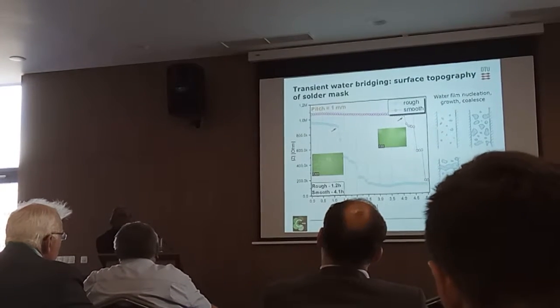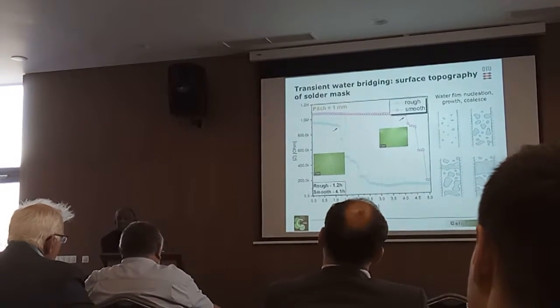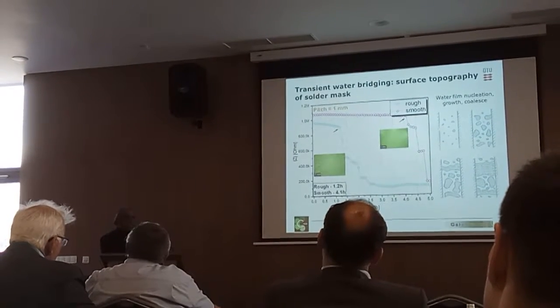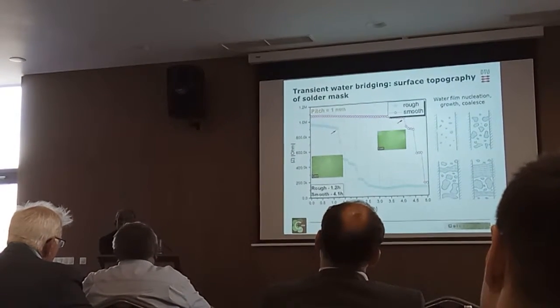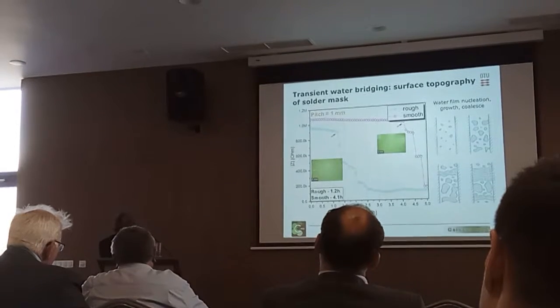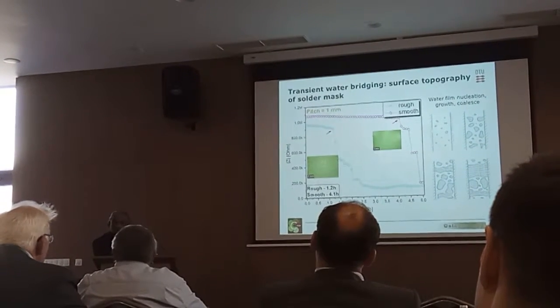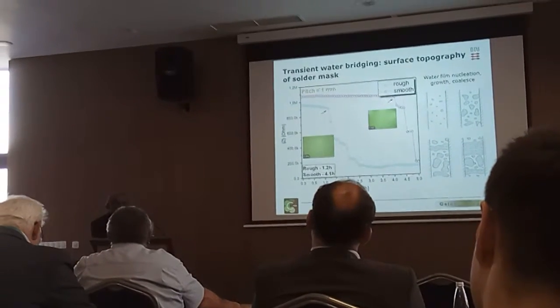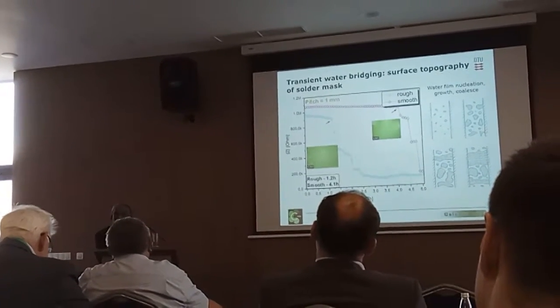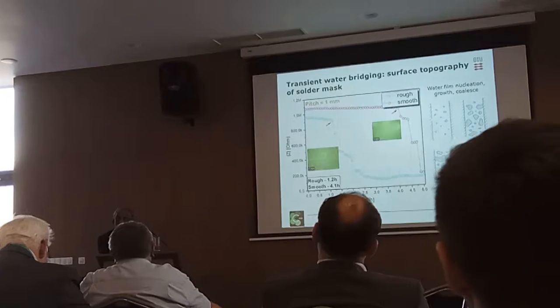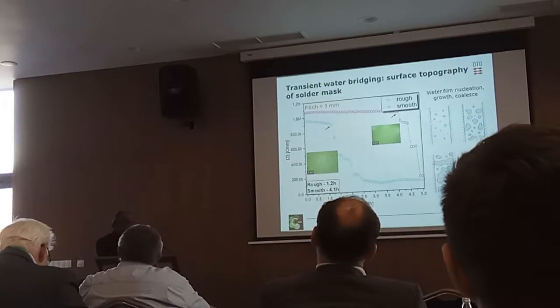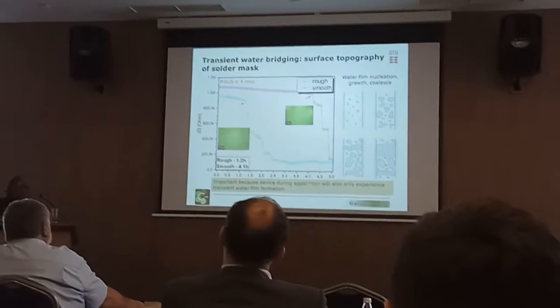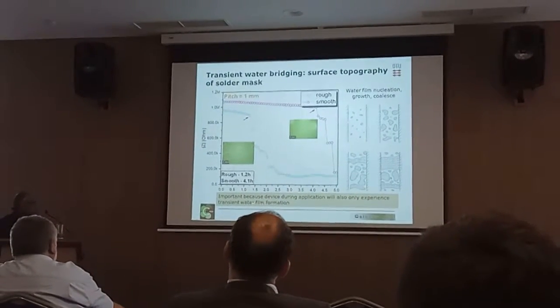So which means that if you can delay the continuous water layer formation transiently for a period of time, that is the important factor — and that way you will be able to improve the reliability. This is what we are looking for — we are trying to see how they can optimize the surface morphology so that this water bridging can be reduced, and they can get much more reliability during the transient condensation period.